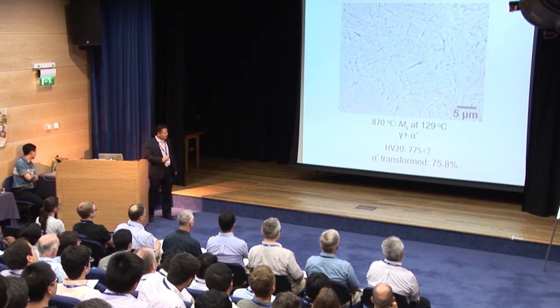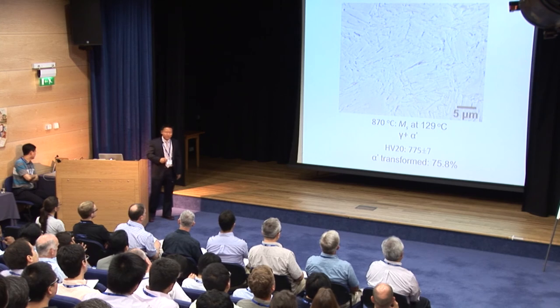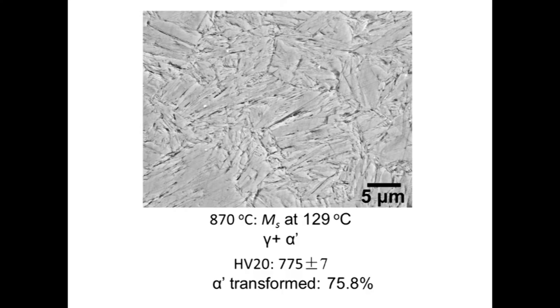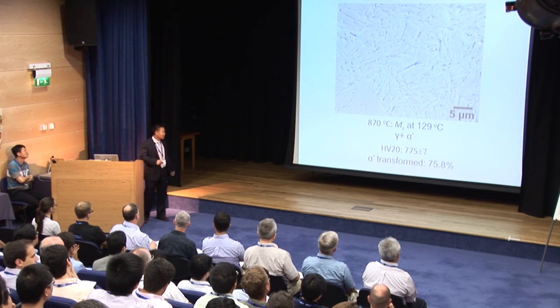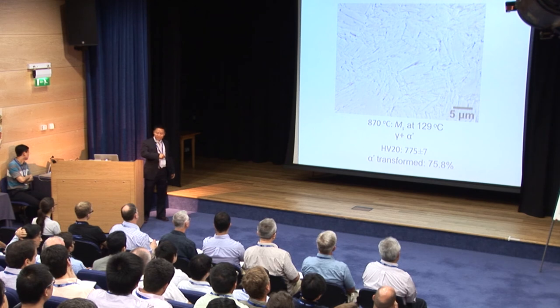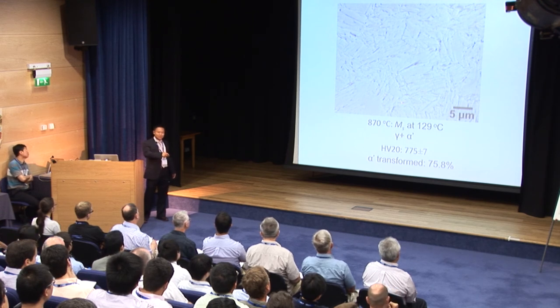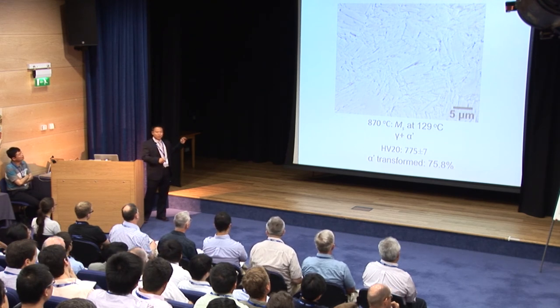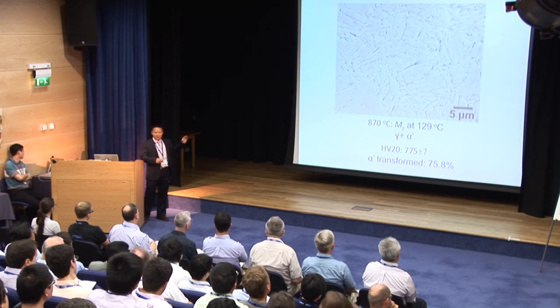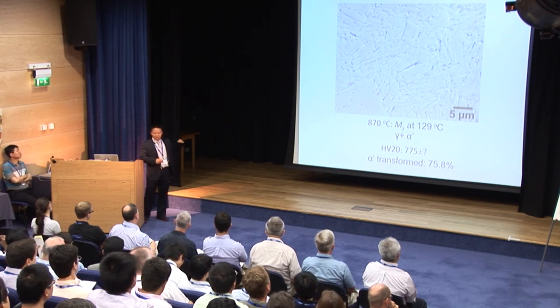As I said, the problem is that this is the first experiment for the new alloy system. At this moment, we kept isothermal holding at the heat treatment temperature for only 10 minutes in the dilatometer. After that, I found maybe it's too short, because the dilatation curve is still decreasing, the length of the specimen is still decreasing. That means the phase transformation did not reach